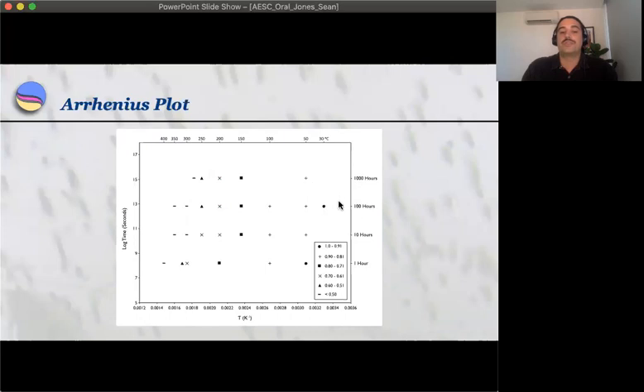Each one of these points represents a single annealing experiment that has been averaged across both surface orientations, and the normalized track length values are calculated relative to the average length of the unannealed control samples, which is 10.6 microns. In the plot, the normalized track length values in a particular range are represented by the same symbol and exhibit linear trends with positive correlation.